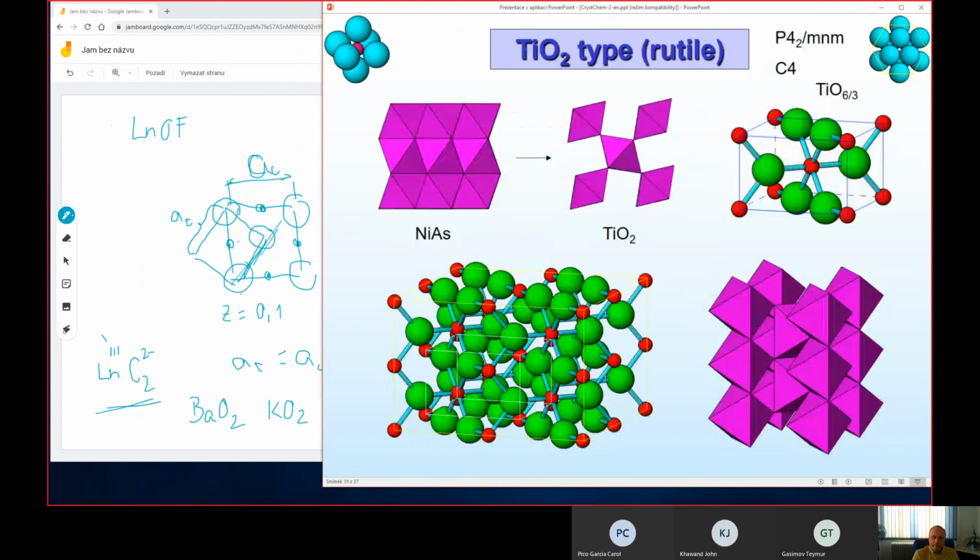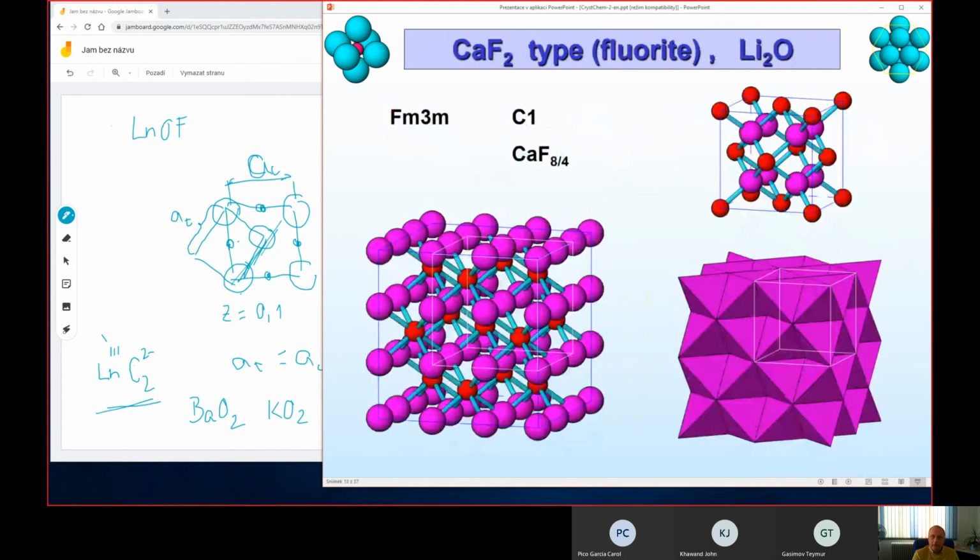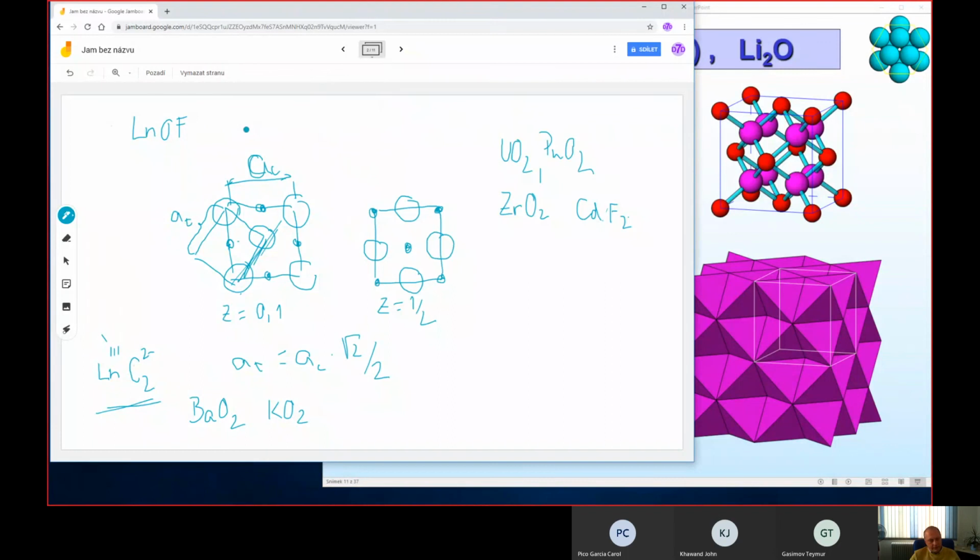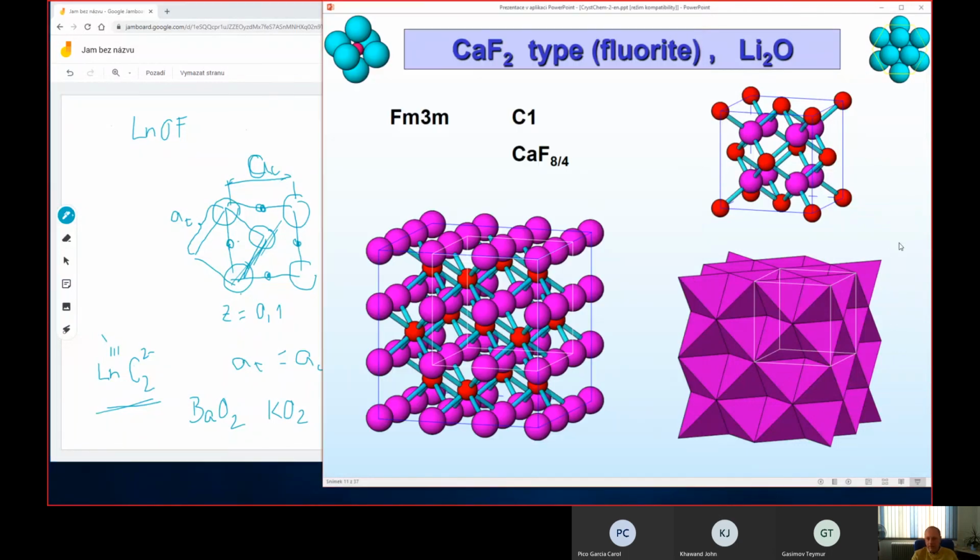Also here, we can also place some clusters like coordination complexes. So for instance, the compound K2PtF6 can be viewed as a close-packed array of these clusters or complexes, and the cations occupy the tetrahedral sites in this close-packed array, and so on.